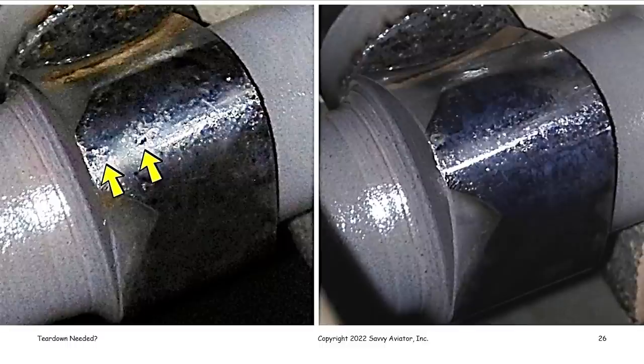It's a thin outer hardened layer, about 15 thousandths of an inch thick, that provides very good wear characteristics because it's very hard. The fact it's very hard also means very brittle. So they can't through harden the cam because it would become very brittle and it might break.